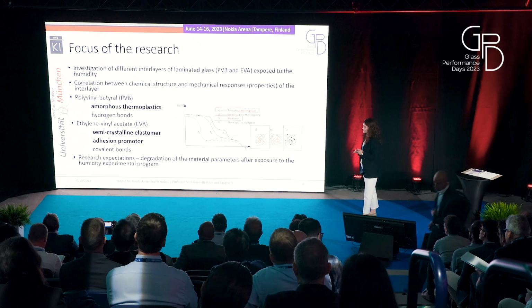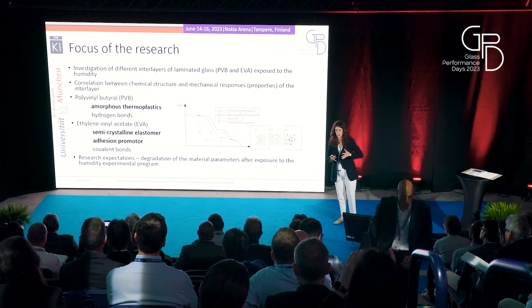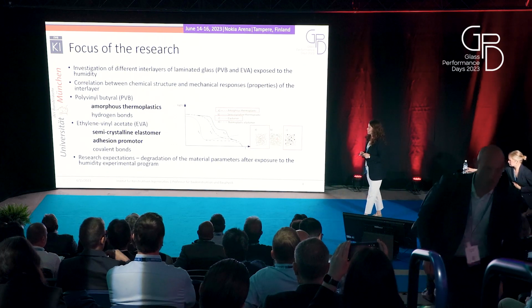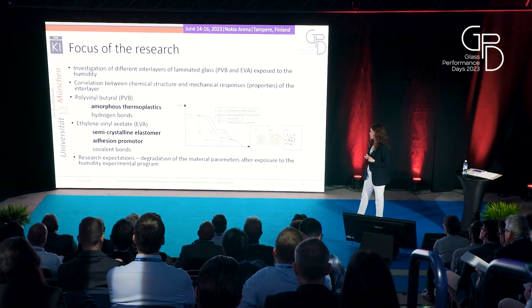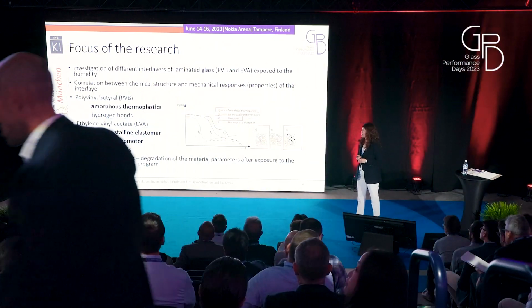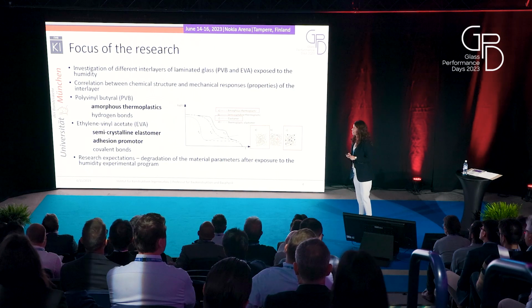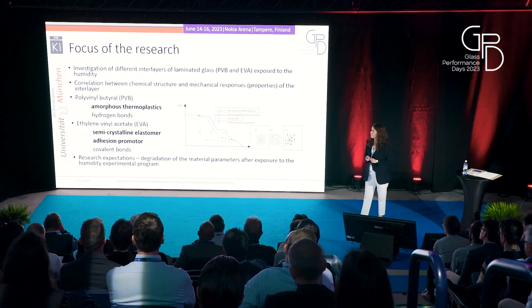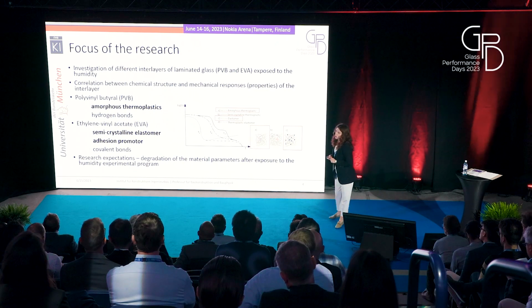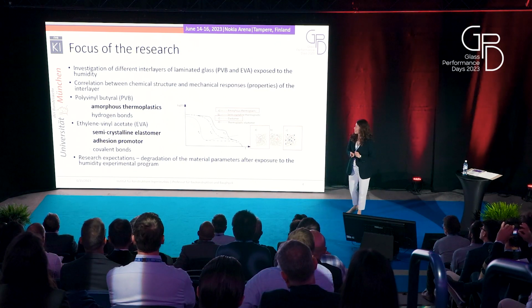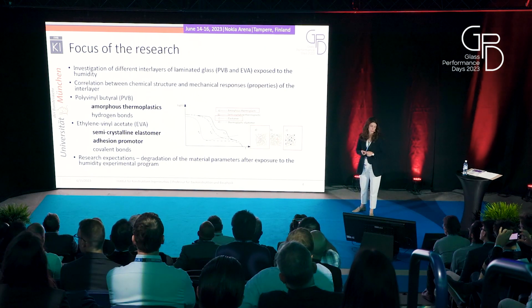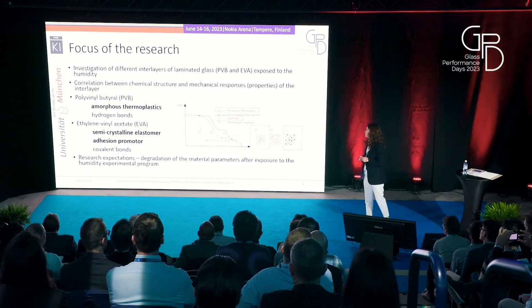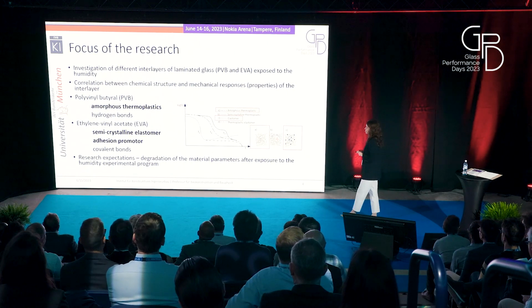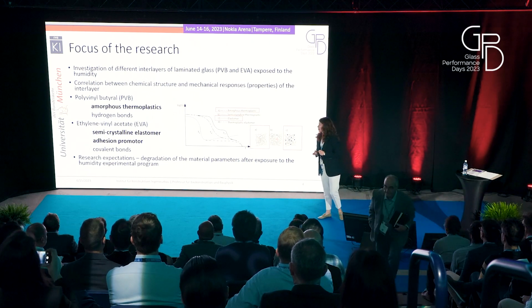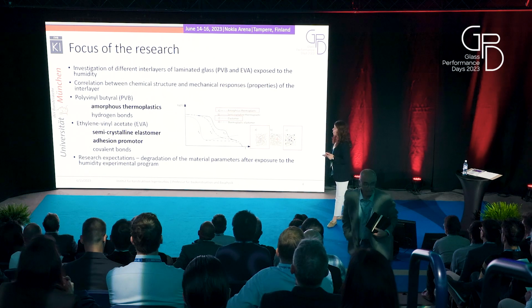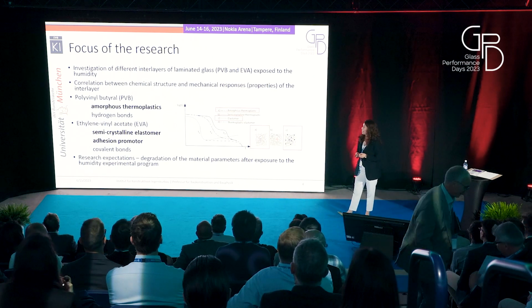This research is actually just a part of our bigger research regarding laminated glass, and this is just one part of it that we recently did. Through this presentation, I will show you the investigation that we did among different interlayers which were exposed to humidity. We put a focus only on two interlayers here. We chose the most common one, which has been used pretty often, the PVB, and we also put a huge focus on the EVA. What we try to find is a correlation between the chemical structure and the mechanical responses of the interlayer.